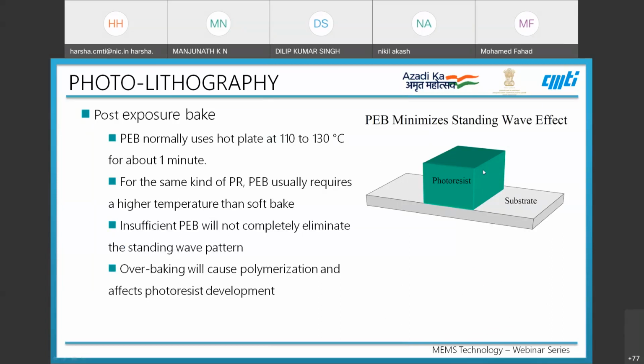The post-exposure bake uses a normal hot plate at about 110 to 130 degrees for about a minute. It is generally at a higher temperature compared to the soft bake used before. For the same kind of photoresist, the PEB usually requires a higher temperature, and insufficient PEB will not completely eliminate the standing wave pattern. The purpose of this step is to eliminate the standing wave pattern. If we do not optimize the process with proper temperature and time, insufficient PEB will result in the standing wave pattern again. If we increase the temperature and time too much, overbaking will cause polymerization and affect the photoresist development, which we will see shortly.